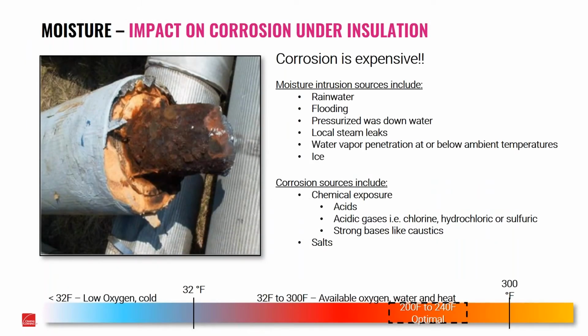So again, the impact of corrosion, just to talk about it, and this is only one slide for those of you that have seen too many CUI slides. Corrosion's expensive. What happens is we have moisture that gets into our system because of any of these items below: rainwater, flooding, pressurized cleaning, wind-driven rain, a lot of times vapor penetration into the system. So there's a lot of ways that moisture can get in. You can never make it completely vapor tight, at least on a high temperature application. If you're doing low temperature, then you have to pay particular attention to detailing there. Hotter systems are a little more forgiving that way.